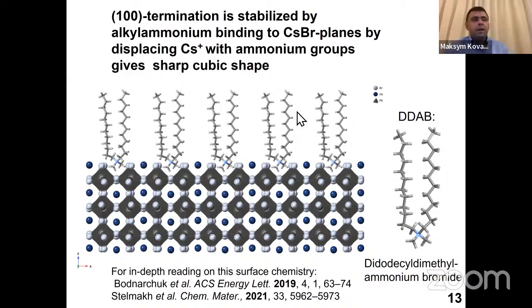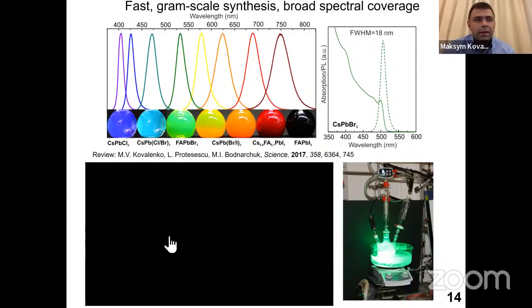surface facet. And so because of this mechanism, your nanocrystal definitely prefers to expose only 1,0,0 facets, and therefore you end up with a cubic shape. As a little spoiler, I will show you that you can actually use some other ligands, and therefore you will have different shapes. But in the initial first edition of this material, we had cubic shaped nanocrystals. Now let me start speaking of the problems.